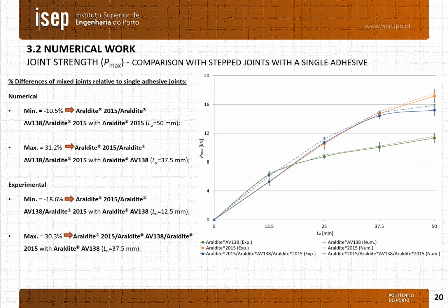The stepped lap joint strength comparison between the dual adhesive and the single adhesive configuration is performed in this slide. In the numerical results, the minimum difference is minus 10.5% when compared to the single adhesive Araldite 2015 and for an overlap length of 50 mm. The maximum difference is 31.2% in regard to the single adhesive AV138 and for an LO of 37.5 mm. Regarding the experimental results, the minimum difference observed is minus 18.6% when compared to the single adhesive AV138 and an LO equal to 12.5. The maximum difference is 30.3% in regard to the adhesive AV138 and an overlap length of 37.5 mm.